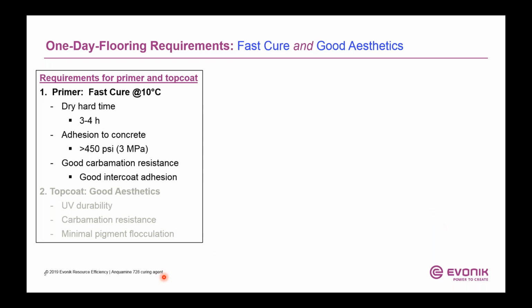For one-day flooring, there will be requirements for the primer and the top coat. For the primer, it needs to be fast cure and also cure at low temperature. The strawman model we get from our customer voice is the primer needs to dry within 3 to 4 hours at 10 C and high humidity, and should have excellent adhesion to concrete substrate and good carbamation resistance to ensure intercoat adhesion to the top coats or the mid-coat.